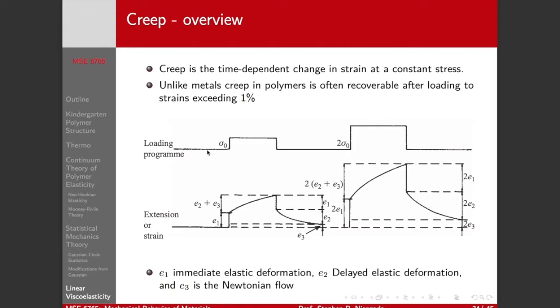So when we're going to go through a loading schedule like this, no load, we're going to add a stress, hold that stress constant, release it, hold it at zero stress for a while, and then add a load in that's twice as big as the original. Hold it, release. So what happens to the strain? Nothing, nothing, nothing. We apply the stress. We get an instantaneous strain. That's our elastic response. And then we get a time-dependent creep where the strain slowly increases with time, and the rate of that extension decays with time.